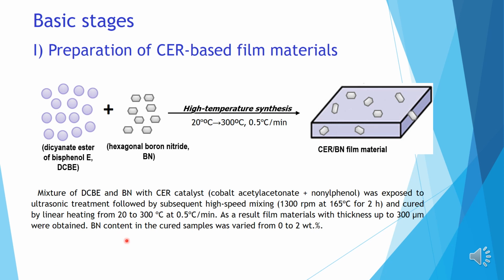In the first stage, we prepared CER-based films from dicyanate ester of bisphenol E and boron nitride in the presence of a catalyst through high-temperature synthesis under the following regime. BN content in the cured samples was varied from 0 to 2 weight%.